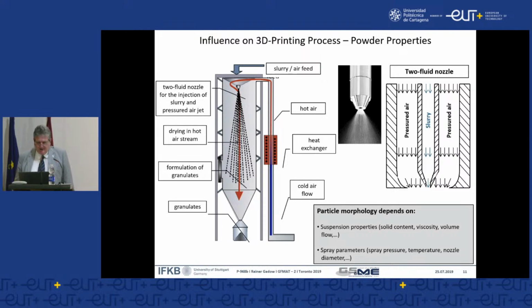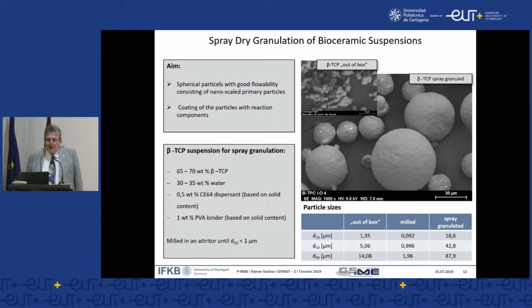Further important properties are the viscosity of the suspension. All the suspension properties are essential: solid content, viscosity, the volume flow, the pressure, the opening size of the nozzle, and the spray drying parameters in such a device. So that was really more than a year of work to obtain the appropriate set of reproducible parameters to obtain the appropriate powder material. That is how it looks.